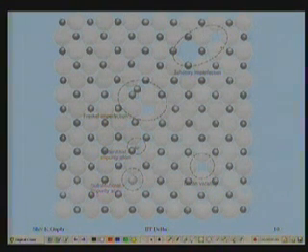Is that clear? The other most commonly seen defect is a Frenkel imperfection, whereby a cation displaces itself from its regular site and goes and sits in another interstitial void. This is its regular site and this is not its regular site. Not that it is going and sitting close to the next cation, but in some other interstitial void space nearby in the neighborhood. I am talking about a three-dimensional structure. So this displacement of a cation from its regular site to an interstitial site is what is called a Frenkel imperfection. In here, there is no problem of charge neutrality.